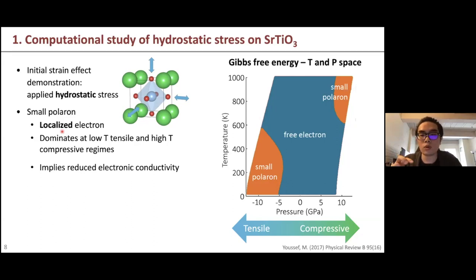Since the electron is localized, when it wants to transport, it cannot move as easily as the free electron because it has to hop from one titanium to the other. So this gives them very different transport properties. And in this predominance diagram, we have shown that the free electron basically dominates most of the region, and the small polaron only dominates at the high temperature compressive region and the low temperature tensile region.